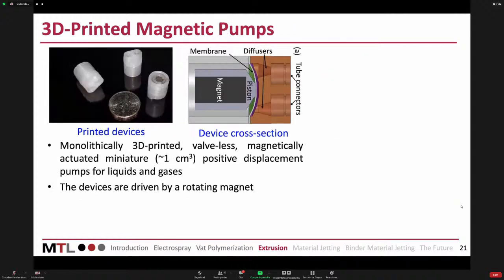And this is a pump. So it's a magnetic pump where the piston has a magnet, and we have these diffusers that allow us to cycle the liquid without having to resort to valves. So it's a valveless system. And to give you an idea, this is on the order of 1 centimeter. So this design is pretty neat because it's not your typical back and forth positive displacement pump. This is the best way I can describe it. This is like a bell. It goes like this, like back and forth, and that's how you push the material.